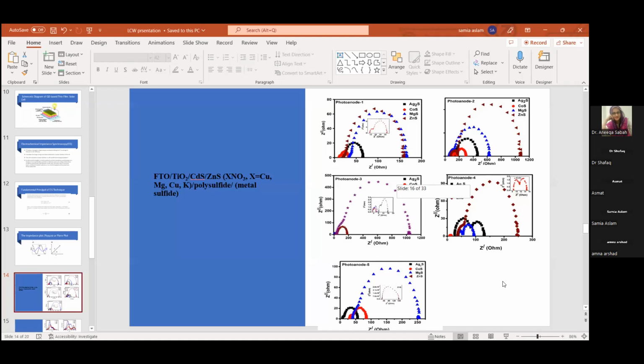And then if we talk about the counter electrode, here it is known as charge transport resistance. It means how the counter electrode side is basically taking part in the reduction process, where it gains electrons and then releases them to the electrolyte so that they move on the other side to reach the photoanode. So when we are assessing it with respect to the counter electrode side, we say that the charge transport resistance should decrease, because if the charge is transporting easily, the resistance should decrease. So the width of the circle should decrease. So for the photoanode side, it should increase, and for the counter electrode side, it should decrease. So in this way, we can interpret